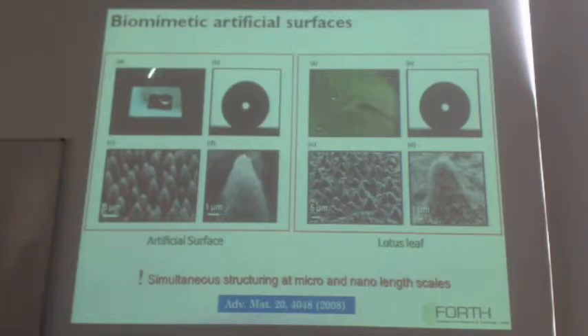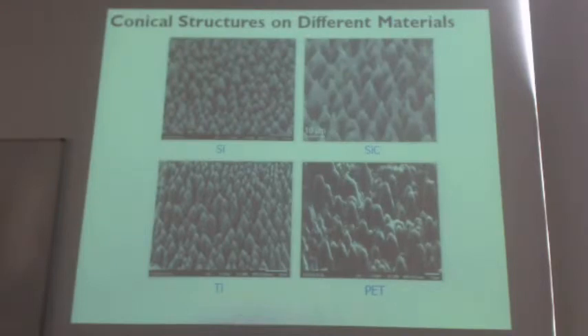The similarity between the artificial and the natural surface, as you can see here in this transparency, is remarkable, both in terms of morphological characteristics as well as in terms of the hydrophobic properties. You can see here that both the artificial and the natural surface comprise these microconical structures that are decorated with protrusions at the nanoscale. And this technique is actually universal. We can have this type of microconical morphology on different types of surfaces, including semiconducting, metallic surfaces, and polymeric ones.